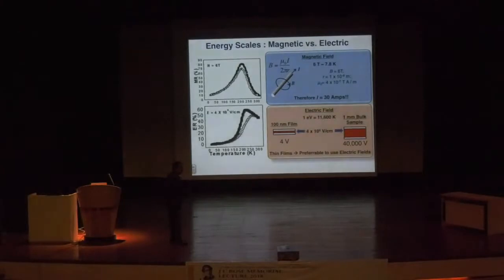If I have a wire, you can use Ampere's law, or Biot-Savart's law, and calculate the magnetic field. For a 6 Tesla magnetic field at a distance of a micron from this wire, you need a current of the order of amps. Whether it's 30 or 25 is really not a big deal. It's of the order of amps. Okay. And for that kind of a current, you need a big battery which is pumping it through.